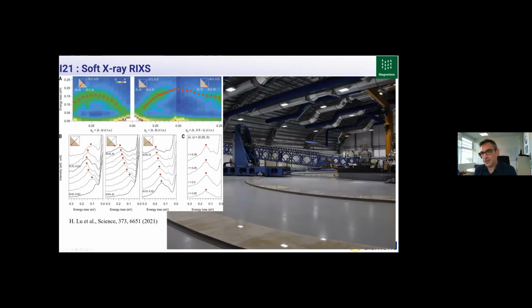So this is the imaging group. I'll switch now to the magnetic and quantum materials group. I guess one of the new babies in the suite of instruments that we have at Diamond is this soft X-ray RIXS beamline. This is a technology, as you know, that has been really pushed in the last decade, going from typically something around an electron volt energy resolution down to typically 30 milli-electron volts nowadays at the copper edge, and even lower if you go to the oxygen edge, where you can reach 15 meV. And this beamline is very impressive in terms of count rate.